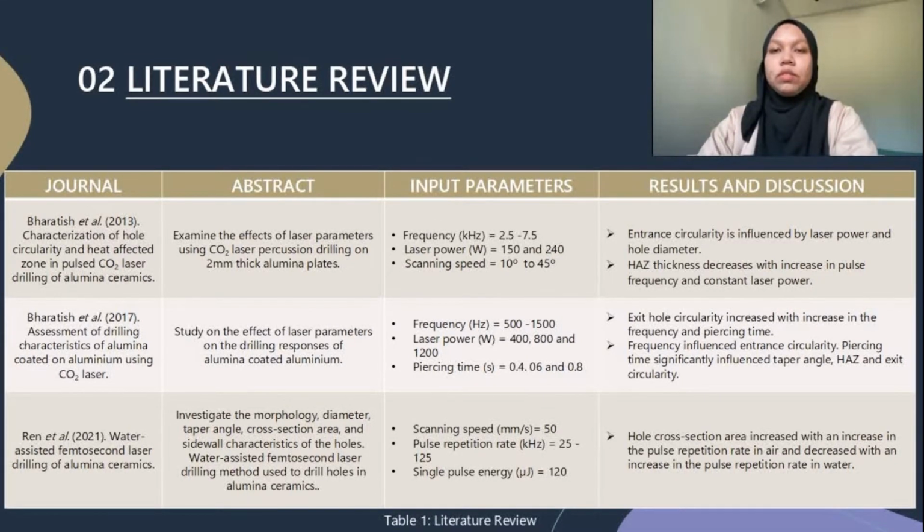Secondly, Bharatish et al. (2017) studied the effects of laser parameters on the drilling responses of alumina-coated aluminium. The machining parameters used are frequency, laser power, and piercing time. From the journal, the results stated that exit hole circularity increased with an increase in the frequency and piercing time. Other than that, frequency influenced entrance circularity. Piercing time significantly influenced taper angle, HAZ, and exit circularity.